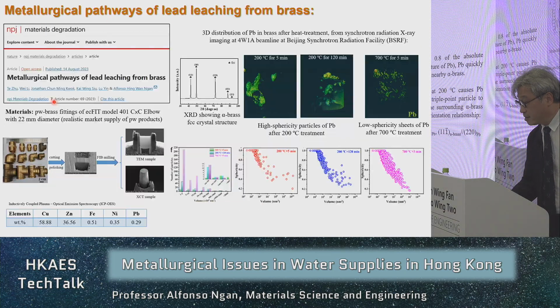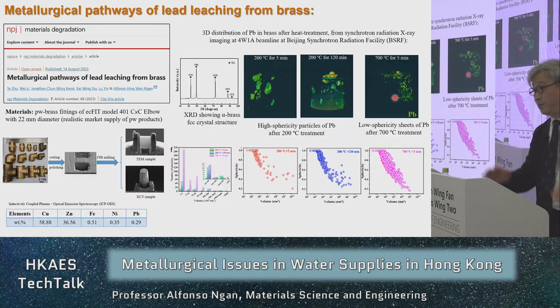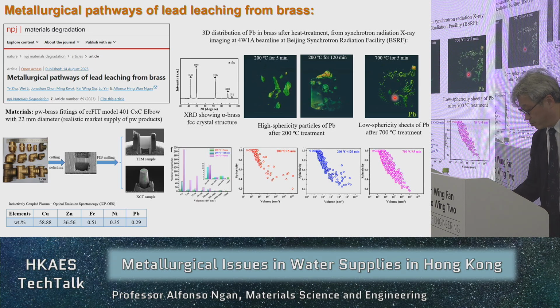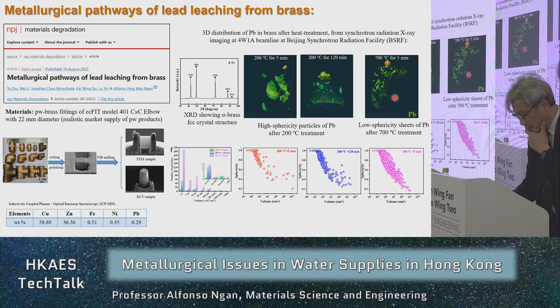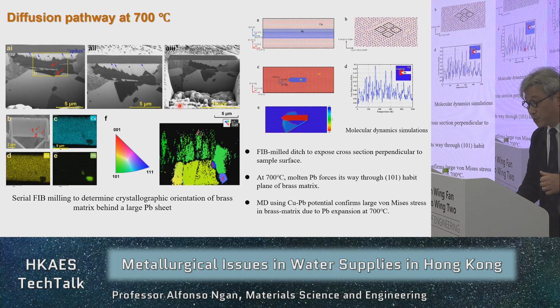Quite interesting. At a higher temperature, 700 degrees Celsius, the lead inside the copper would have melted, so become liquid. The copper is still solid, right? Then the lead content, as I said, would become more sheet-like, more plate-like, with reduced sphericity. So as we look at them, we saw a lot of plates. All these spikes that you can see there are not really spikes, they are sheets of lead.